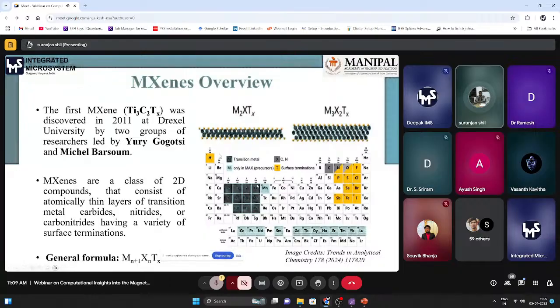You can see in this periodic table how we can make this experimentally. People synthesize with this kind of transition metals, and mostly carbides and nitrides are synthesized. Others may be possible, but carbides and nitrides are the most available MXenes, and they have the general formula M(n+1)XnTx. T is the termination, meaning that when you are making a 2D material of MXene, let's say a metal carbide, you need to terminate the surface with some other atoms. It's mostly non-metals. If you see here on the right side of the periodic table, phosphorus, sulfur, fluorine, this kind of atoms, you can terminate with those and make nice 2D MXenes.